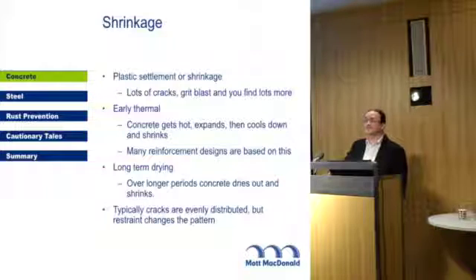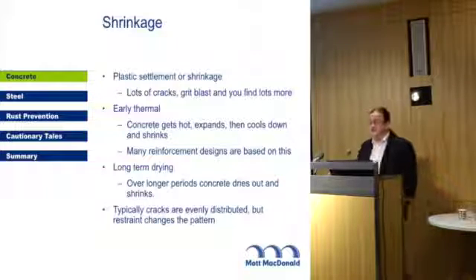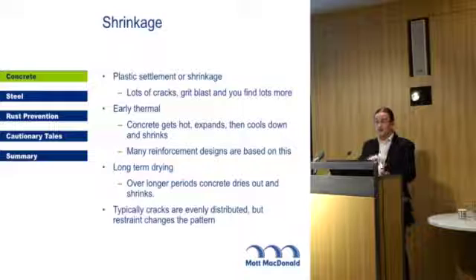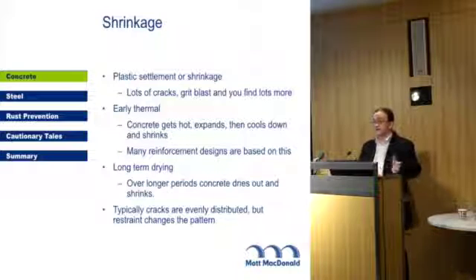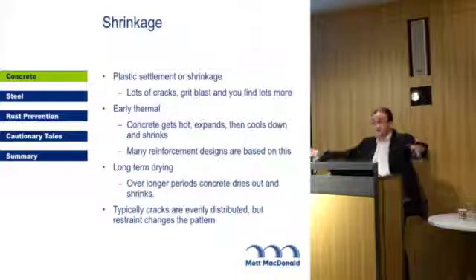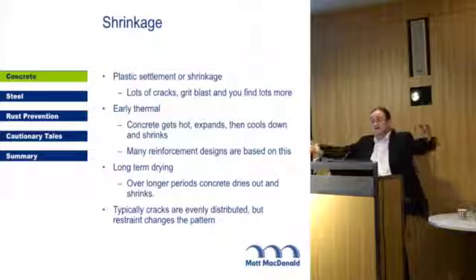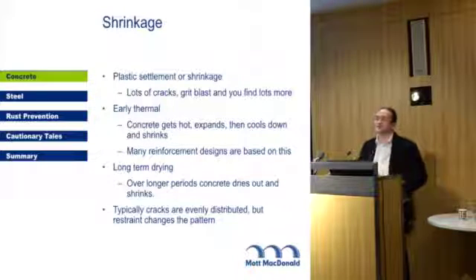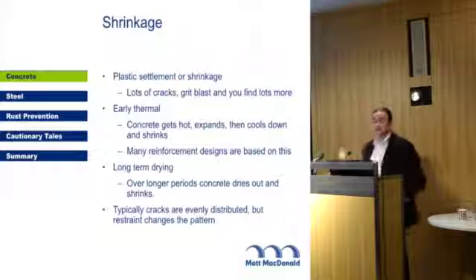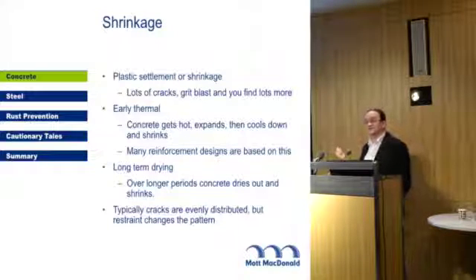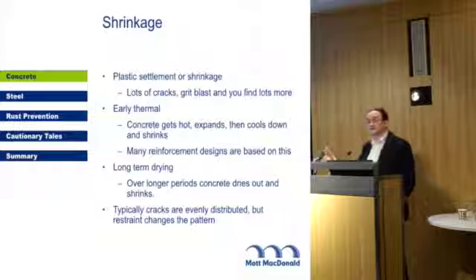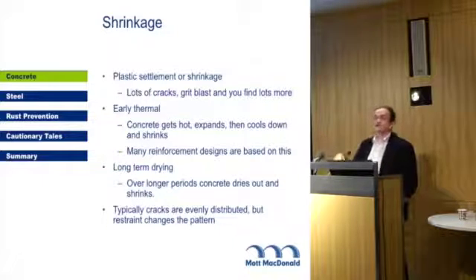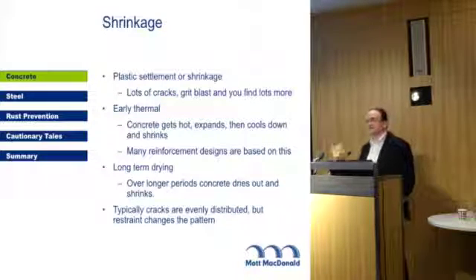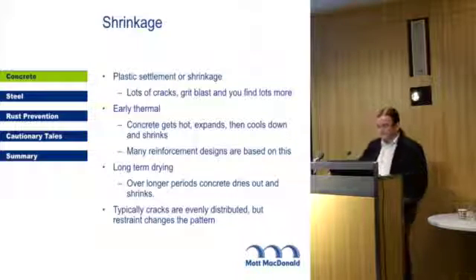Early thermal cracking is cracking due to early thermal effects. Basically, concrete going hard, chemical reaction, gives off heat. So it gets hot and expands. Then it goes hard and cools. And as it cools, it shrinks. And as it shrinks, it gets tension in it. So you get cracks. And a lot of reinforcement designs are actually based on this. It's kind of handy when you come to fix a motorway pier, because it means, yes, you've got lots of corrosion, but structurally it's not that significant because we put a lot of steel in to cope with the fact that it was hot and then got cold.